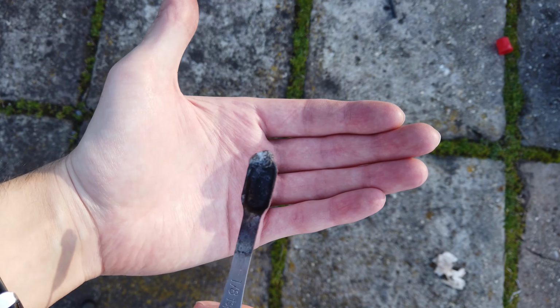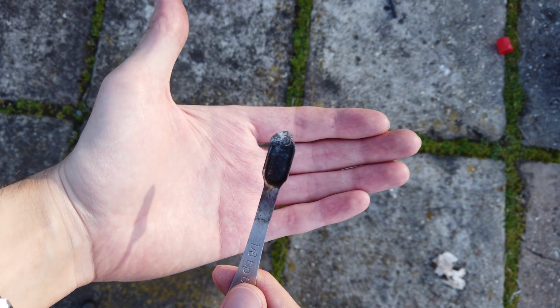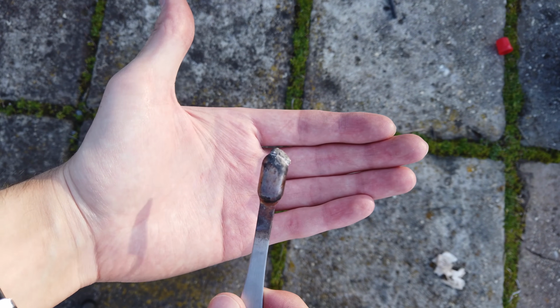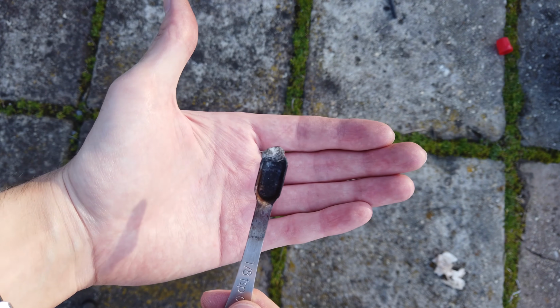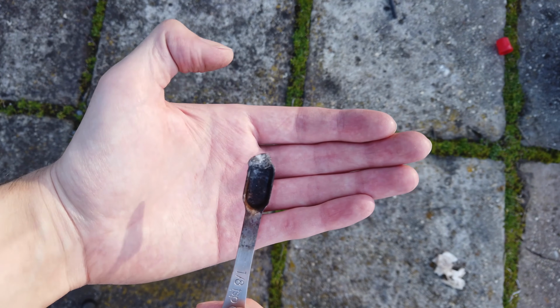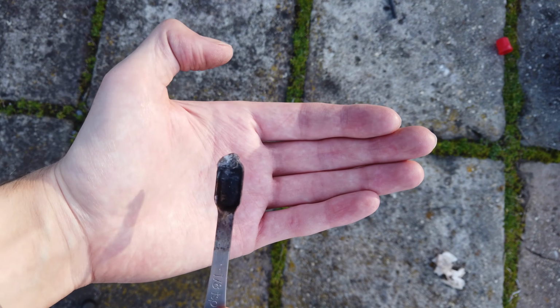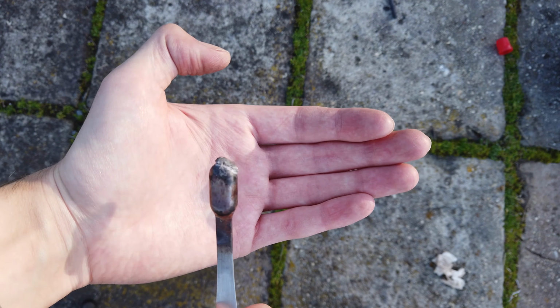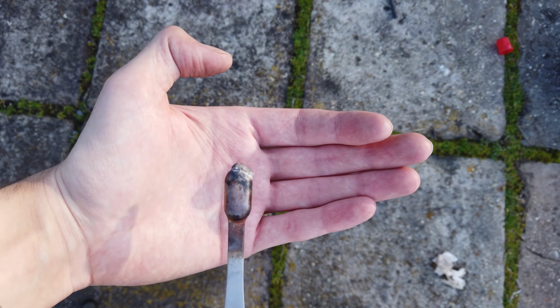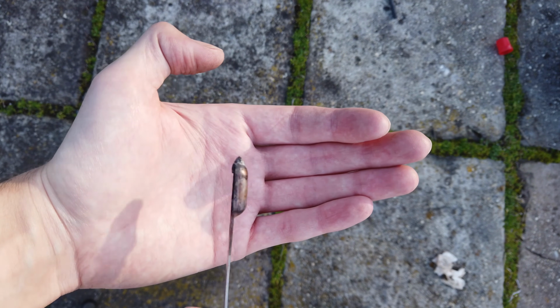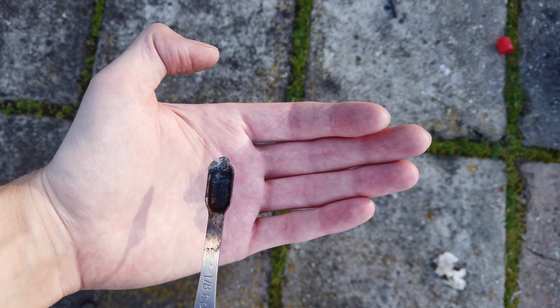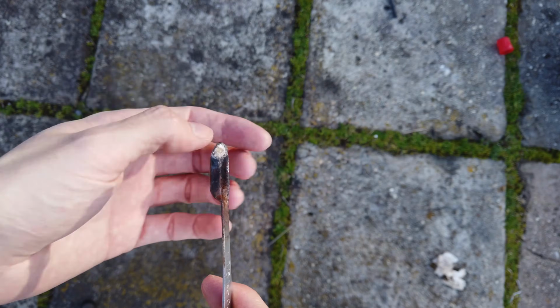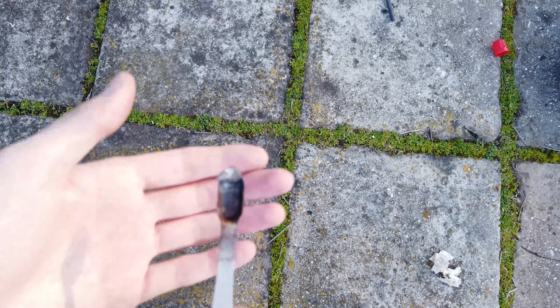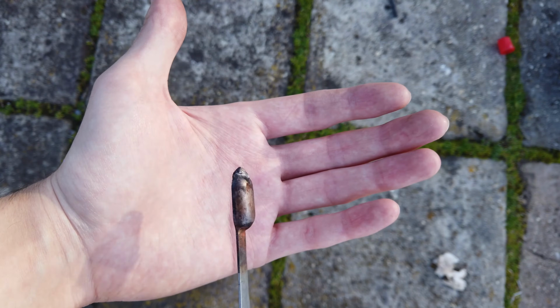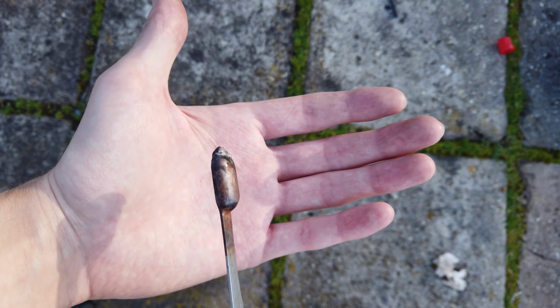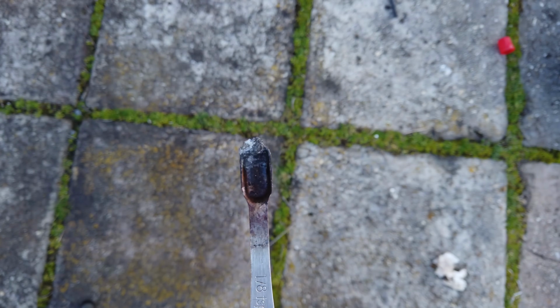And yes, after another 15 minutes of electrolysis, you can see we have actually made a small amount of calcium. It doesn't look like much at the moment. It doesn't look quite as shiny as it should because it has oxidized in the air a little bit. It's gone a little bit white, a little bit black. I'm also really struggling to take it off the scooper that I used to collect it, because while the molten calcium chloride doesn't really stick to it, the actual calcium itself has really stuck. So I'm going to continue trying to get the calcium off this thing, and then we're going to continue electrolysis to see if we can make some more.